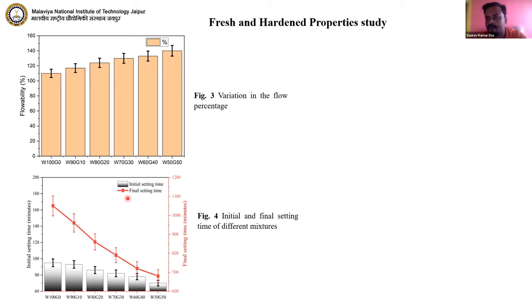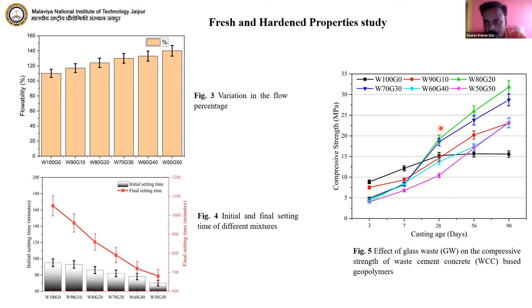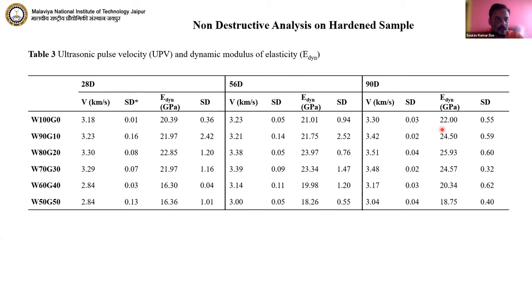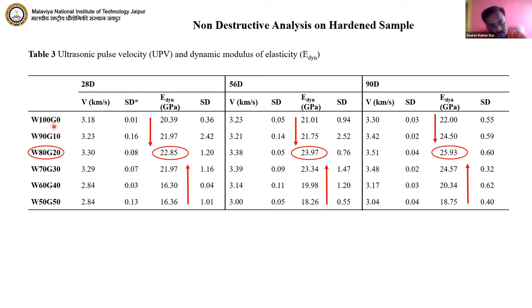And these are the compressive strengths up to 90 days, and you can see that the highest is obtained by the 80% and 20% replacement, where 80% is your waste cement concrete and 20% is your glass waste. So this is the optimum mix we found from the compressive strength test. And then this is the UPV. UPV also relates with the compressive strength, the W80-G20 mixture obtained the maximum dynamic modulus of elasticity.